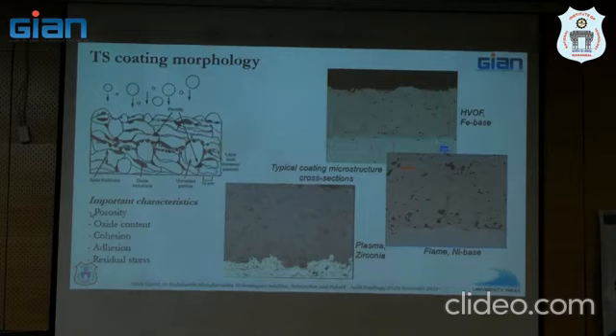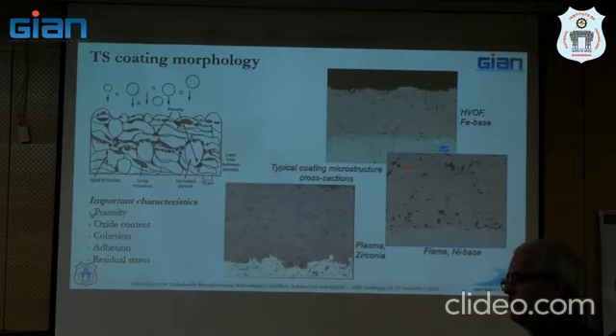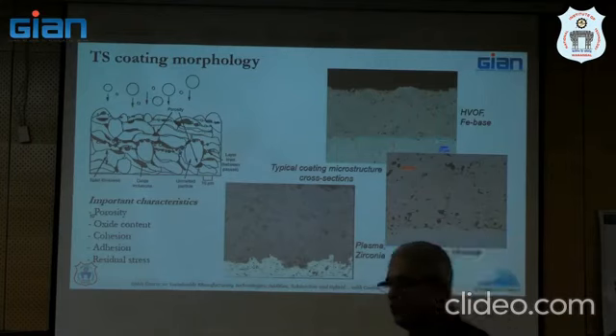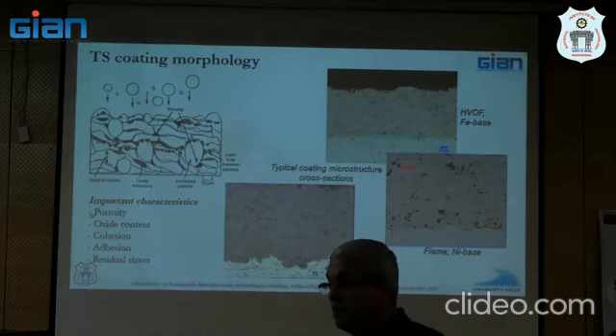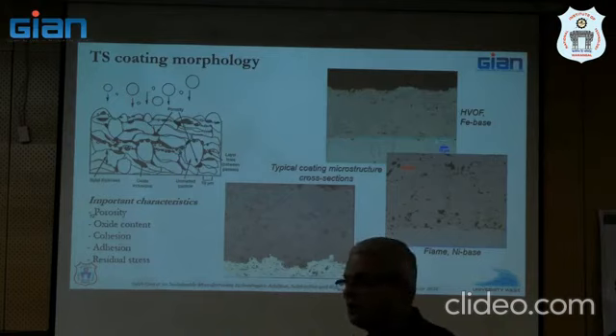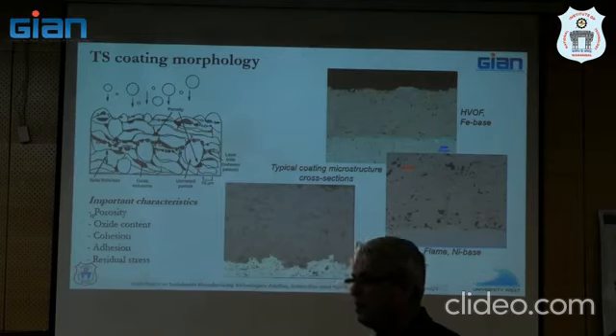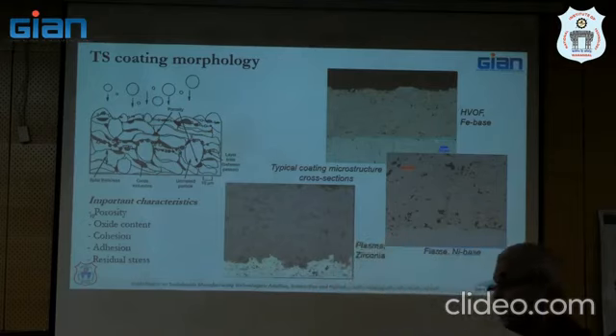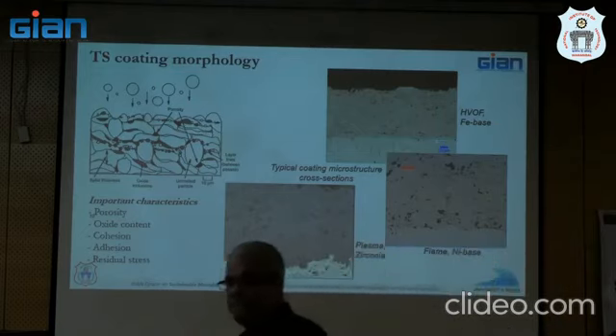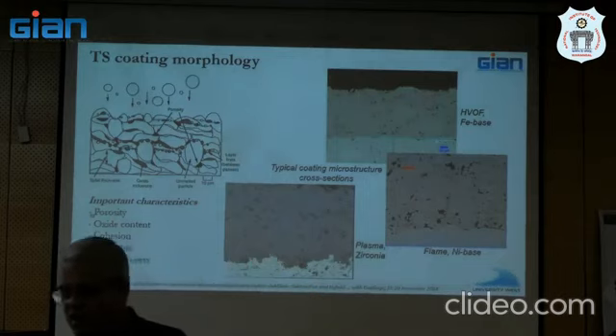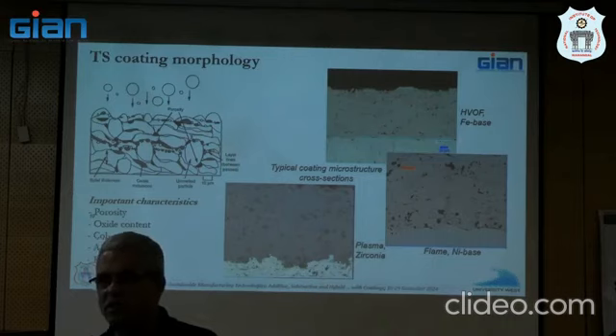Reduce the heat? Yeah, it kind of reduces the thermal conductivity of the coating, which is what you want if you are putting on an insulating coating. What's the other reason? Imagine a thermal barrier coating which was fully dense, no porosity, no nothing. Would it survive? No, it will not survive because of thermal stresses, right? There is no way to accommodate thermal stresses if it's fully dense, correct? The bonding will be good, but if there is no porosity, there is no way to accommodate thermal stresses.